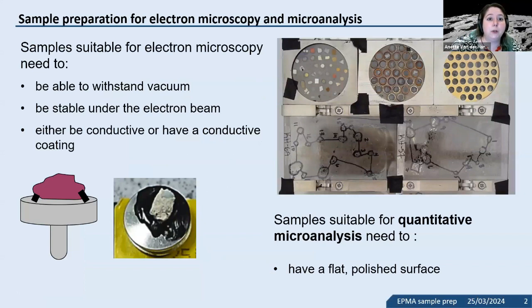So when it comes to sample preparation for electron microscopy and microanalysis, there are certain general rules that they all have to comply with. Specifically even down to electron microscopy, which means that you only want to look at samples, maybe get first order compositional information, but not necessarily the highest precision data. Already, samples have to be able to withstand a vacuum. They have to be stable under the electron beam, and they either need to be conductive or we have to apply a conductive coating, because we bombard them with electrons, and so charging can affect.